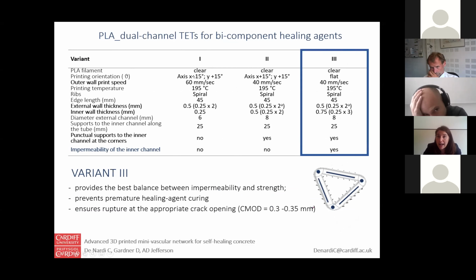Again, we studied 3 variants of the same shape. Basically, we focus on the outer wall print speed and the external and the inner wall thickness in order to make both the channels completely impermeable to each other. And then we add some punctual supports to the inner channel at the corner in order to give more stability to the printing space. Well, the third variant gives the best performance.